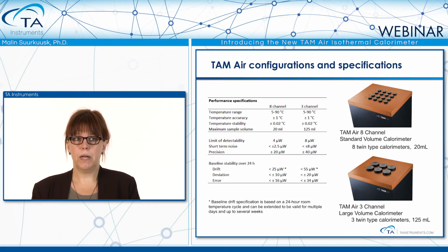If we look at the TAM Air configurations and specifications, we have the TAM Air 8-channel standard volume calorimeter, where you have 20 milliliter calorimeters, and you have the 3-channel large volume calorimeter, where you have 125 milliliter calorimeters. We do specify the thermostat is the same, so the temperature stability is the same. But what we do specify now is a baseline stability over 24 hours.